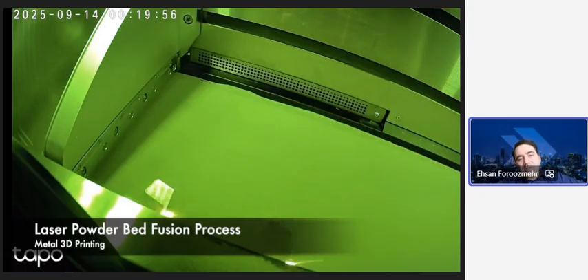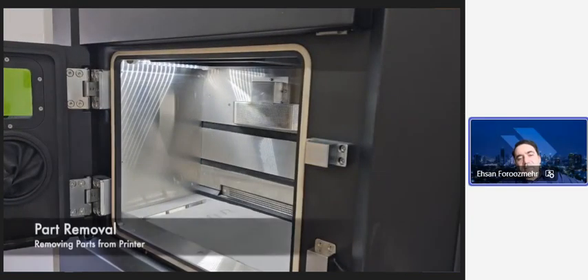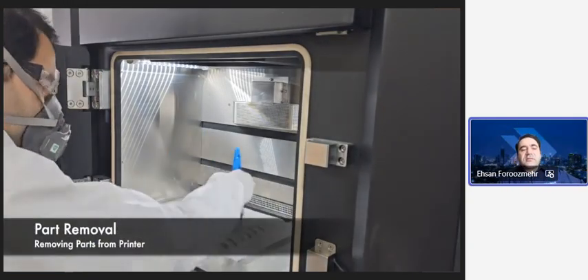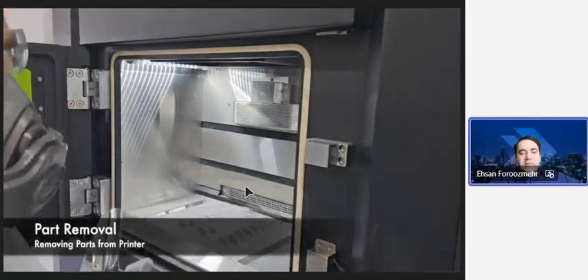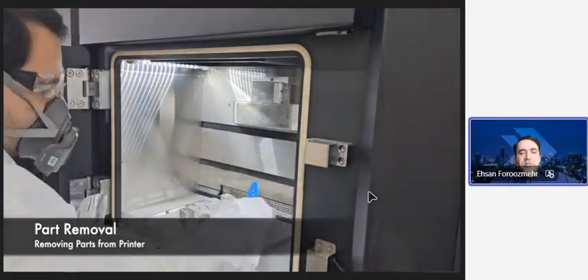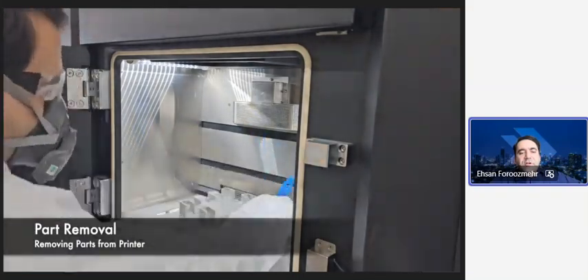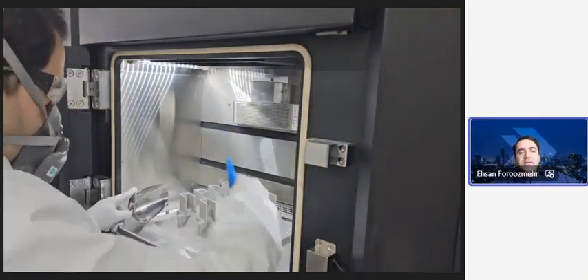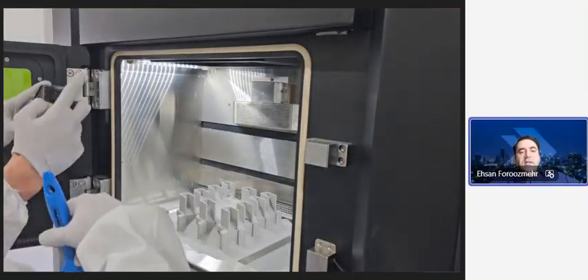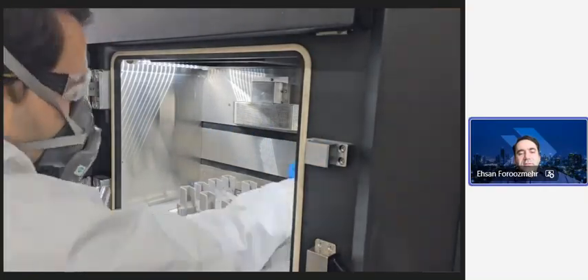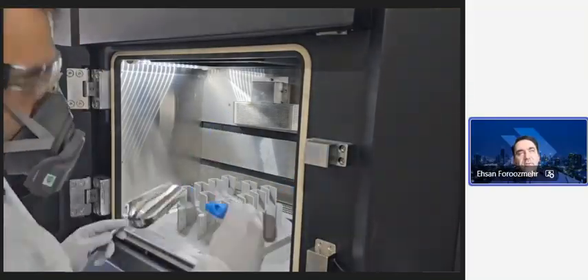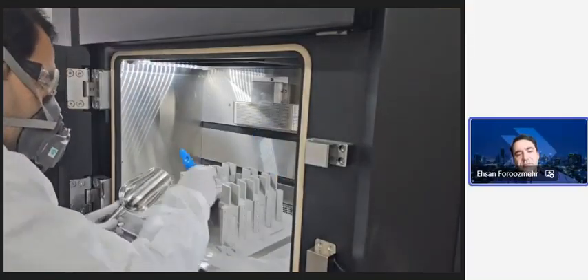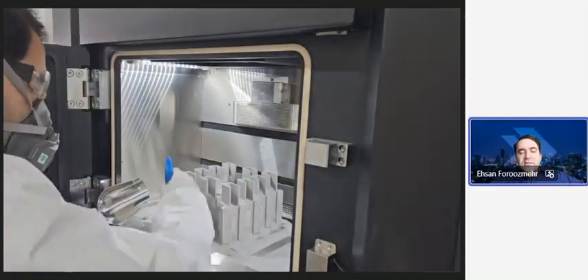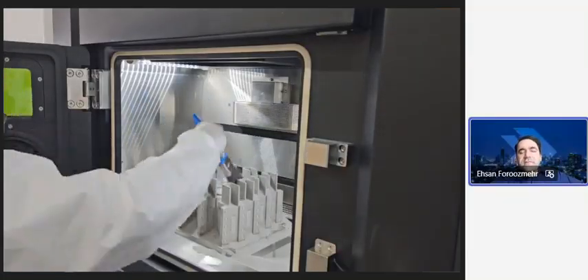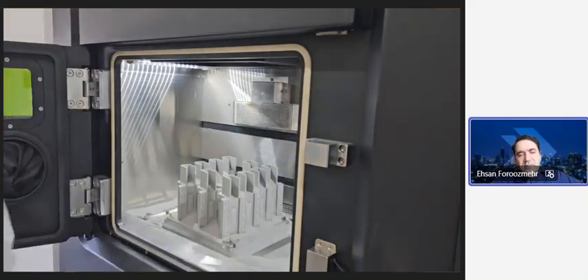So that is the biggest advantage of the technology: the material waste is very, very low because of reusing the powder after printing. As you can see, the part removal happens right after, so the speed has been increased so that it doesn't take much time. The person has to have proper safety gear, mask, and the anti-static hose. The powder is taken off from the part, and as you can see, what is left. The whole process took about 45 hours, and then the parts are pulled out. This batch is about 14 to 16 kilograms of deposition, so that is roughly what we can say.